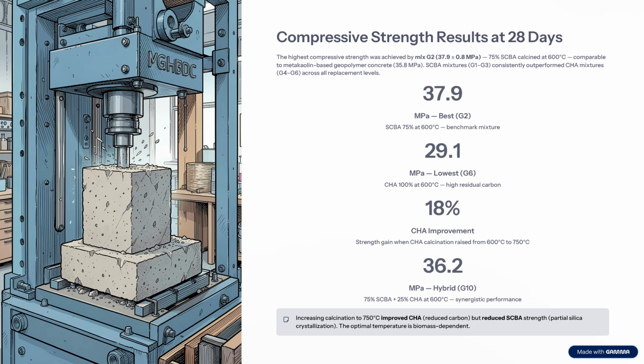For the mechanical performance, the compressive strength results after 28 days. The highest compressive strength was achieved by mix G2, at 37.9 plus or minus 0.8 megapascal, with 75% SCBA calcined at 600 centigrade, comparable to the metakaolin-based geopolymer concrete at 35.8 megapascal. SCBA mixtures G1 to G3 consistently outperform CHA mixtures G4 to G6 across the replacement levels. We can say the SCBA 75% at 600 centigrade benchmark mixture was 37.9.